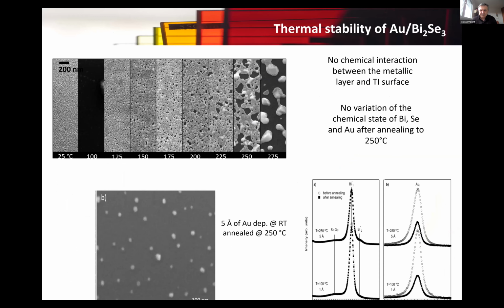So obviously, we can use gold as the metal for electroding. We also wanted to see how that works at elevated temperatures. So we used our heating stage in the SEM, and we have seen that there's no reaction, but the coarsening of the film, and we would get discontinuity in the film. But obviously no interaction, no chemical interaction, even at elevated temperatures. So that's very, very good to know, that we can use gold straight on the surface of bismuth selenide as an electronic contact.